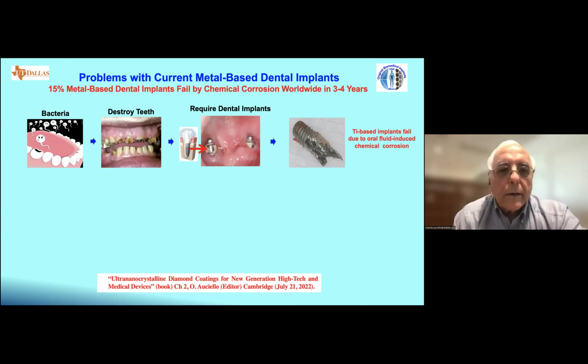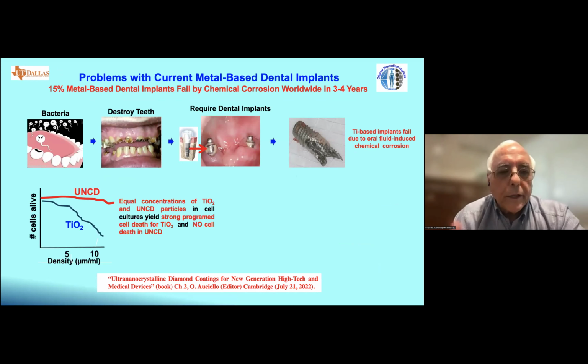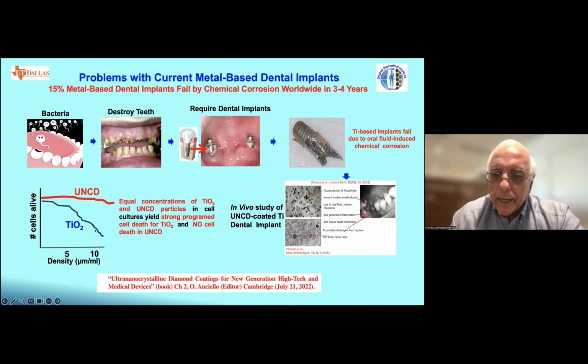What we found about 6-7 years ago when we did the first studies is that titanium oxide particles are dislodged by chemical attack by the oral fluids, and they start killing cells like crazy. They get into the tissue, and we found in the experiments with animals that many of these titanium oxide particles find their way into the bloodstream. Not good.